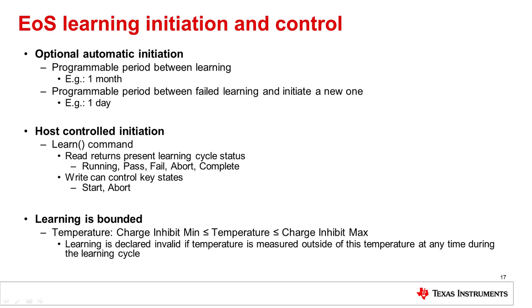The algorithm also includes temperature limits on when learning pulses will actually be triggered. If you are outside a prescribed range — set by flash settings in the device — the learning pulse would be aborted and the device will wait and try again later when the temperature is back in an acceptable range. This is because R cell values, the resistance of the cell, are very dependent on temperature. The device performs temperature compensation when comparing a reading now versus a reading from a month ago or from when the cell was fresh — possibly a year beforehand — captured at different temperatures. If the temperature range is too broad, even temperature compensation has its limits, so you can configure the acceptable temperature range for learning pulses.